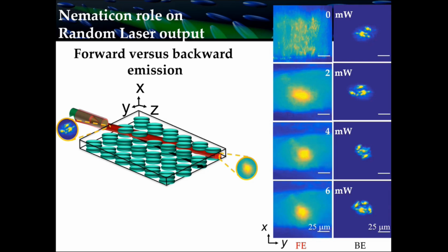And so you see that by changing the amount of power in the green beam for the soliton, I can go from random lasing to a very nice shape in transverse profile, and increase the efficiency and lower the threshold. So apparently this spot is much nicer, and it's definitely much nicer than the spot from a random laser without a waveguide. But what happens backwards, because there is no limitation to emitted photons in the direction of propagation? They are also emitted backwards. So if I look at the backward emission, of course I still have a random laser without the benefit of propagation in a waveguide.